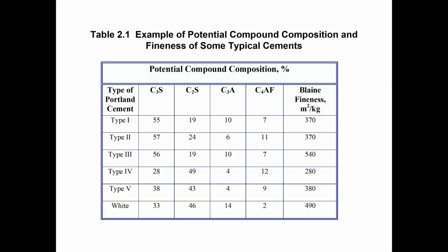Now type 2 is a general use cement as well, but it has some sulfate resistance. And so notice that the key difference between the type 1 and the type 2 is that the type 2 has less C3A. Okay, so C3A is the contributor to sulfate attack. And so since type 2 has some sulfate resistance, it's going to have a lower C3A content. But other than that, and a redistribution of that percentage of C3A to the other components, it's very similar to type 1, and we have generally the same type of Blaine fineness. So we can have a cement that is a type 1/type 2, that meets both qualification requirements.